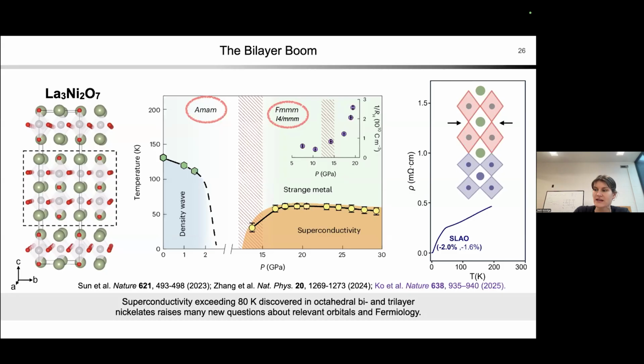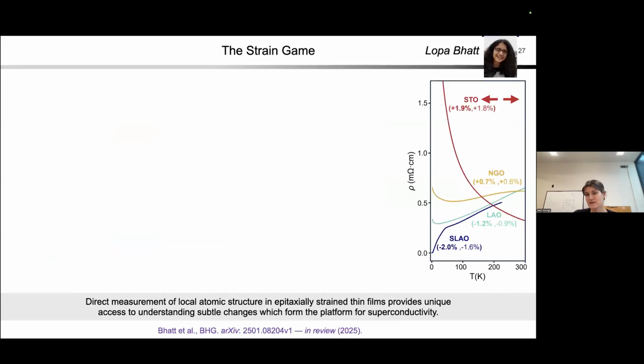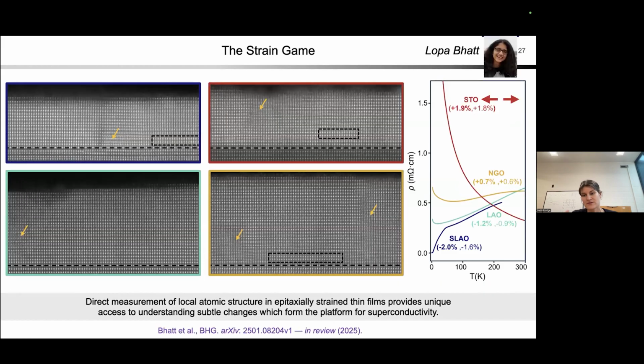So instead of just looking at one sample, we actually wanted to look at a whole series. And so we look at not just the compressive strain case that is superconducting, but all the way up again, going back to that other direction of tensile strain where we're now pulling on the material. And so again, a close collaboration with the synthesis folks who are able to grow a series of all of these different samples. And so this is a lot of work that has been part of the PhD work of Lopa Bhatt, who's here at Cornell, where you can see she's been able to go through and image all of these different films under these different strain configurations.